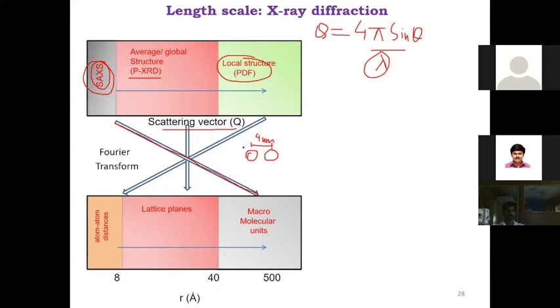Now, if I do a powder X-ray of this gold nanoparticle, we will see the lattice planes, and these come out if you do the Fourier transform. If you use very high Q data and Fourier transform it, we can get atom distances. We can zoom into the gold distances in this material. So from nanoparticle distance with SAXS, to lattice plane, to atom distance, that is basically the bond. If you want to track that, we have to do the pair distribution function of the X-ray.